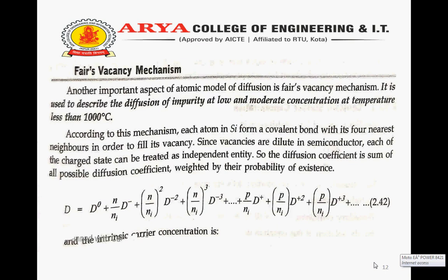Fair's vacancy mechanism. According to this mechanism, each atom in silicon forms a covalent bond with its four nearest neighbors in order to fill its vacancy. Since vacancies are dilute in semiconductor, each of the charge states can be treated as an independent entity. So the diffusion coefficient is the sum of all possible diffusion coefficients weighted by their probability of existence. D equal to D naught plus n upon ni D minus plus n upon ni whole square D to the power minus 2 plus n upon ni whole cube D to the power minus 3 and so on.